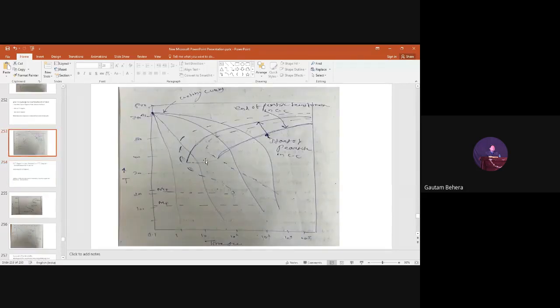Another observation. Can you people tell me any other observations in the TTT and CCT? Increase in incubation period. That's fine, but I've already told you that, the shifting part. Don't tell me those things. TTT is continuous till low temperature, but CCT is not. So towards the lower temperature, the TTT curve is there, but CCT is not. Yes, very good observation.